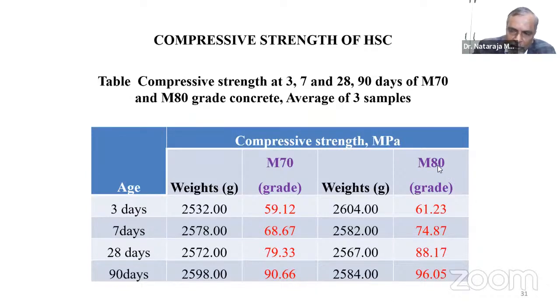As far as M80 concrete is concerned, I need about 86. So I'm getting about 88. And kindly see at 90 days, it is a marginal increase in this strength. And one more important thing, especially for the teachers, I'm sure that the teachers are aware of this particular fact. The strength you are going to get at 7 days in comparison with the grade, almost about 90% of the expected strength you get at 7 days itself. So this is the beauty of the high strength concrete.